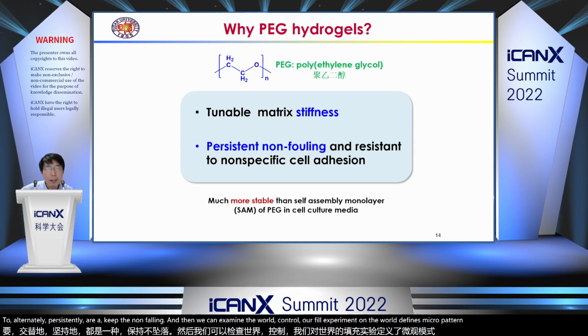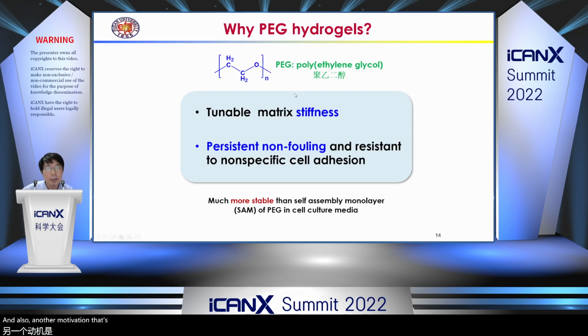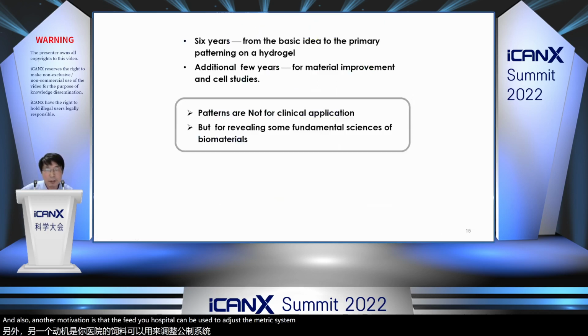And also another motivation is that the PEG hydrogel can be used to adjust the matrix stiffness. However, PEG is inert. You can chemically link RGD to PEG. Also, it is not easy, but it is extremely hard to keep the RGD on the PEG hydrogel in a regular way. Before my group joined in this field, no one could do this.